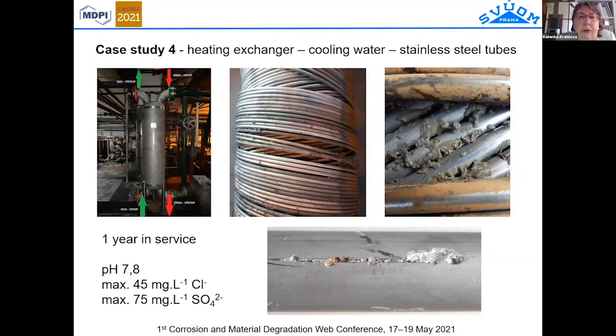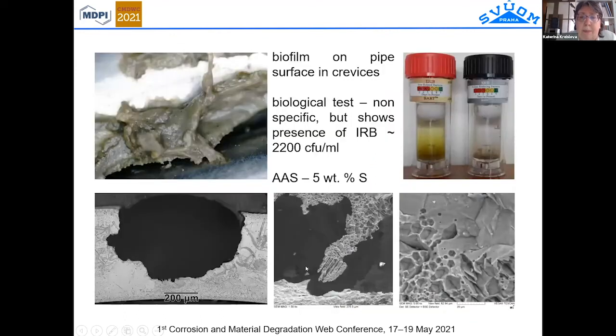Case study 4 was a heat exchanger, which was used for cooling water, also with stainless steel tubes. The problem is that all these relatively small pipes are joined together in spirals. There is a very narrow space between each one, and a lot of biofilm accumulates. There was still such a layer typical for biofilm, and after cleaning, a line of small pits is evident, which occurred just in this crevice between the pipes.